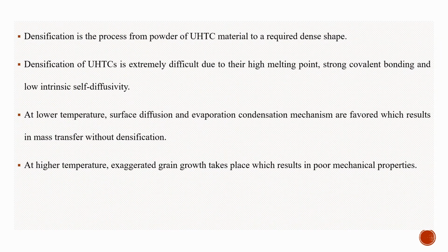Densification is the process from powder of UHTC material to a required dense shape. Densification of UHTCs is extremely difficult due to their high melting point, strong covalent bonding and low intrinsic self-diffusivity. At lower temperature, surface diffusion and evaporation condensation mechanism are favored, which results in mass transfer without densification. At higher temperature, exaggerated grain growth takes place which results in poor mechanical properties.